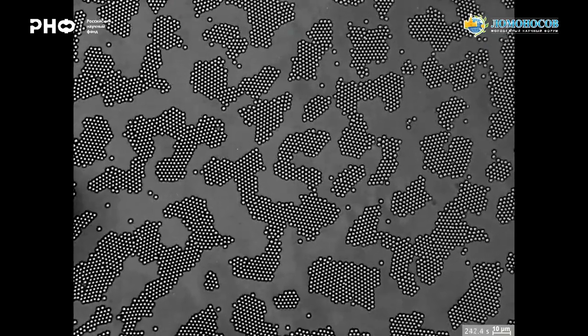So here we see the initially homogeneous liquid layer. Liquid, because we can observe the individual microparticles, and they play the role of quasi-atoms. The structure is homogeneous but disordered, like a typical liquid. And at some moment we apply a rotating electric field and induce attraction between the particles. After some time you can see the formation of droplets, very similar to condensation. And then they become organized into crystalline structures. And if we turn off this field, then we observe the disordered structure again.